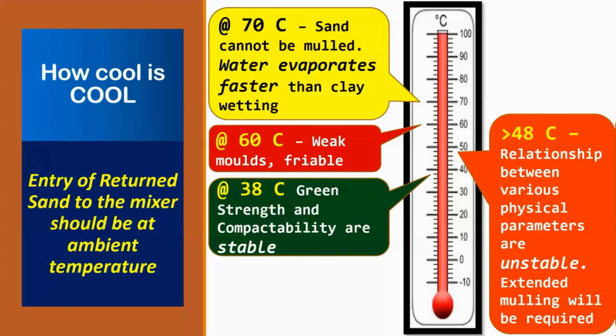So obviously, these 48, 60, and 70 are not the temperature of the sand when they enter the mixer. The mixer needs a very cool sand, which is very close to ambient. Many foundries suffer from this basic requirement in the sand. If the temperature of the sand is higher, then most of the properties will be lost. For example, we are saying water is getting evaporated. So when the water is getting evaporated, the bentonite which you added, if it doesn't get that water